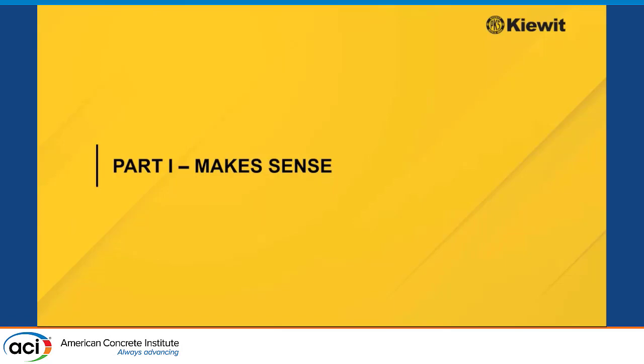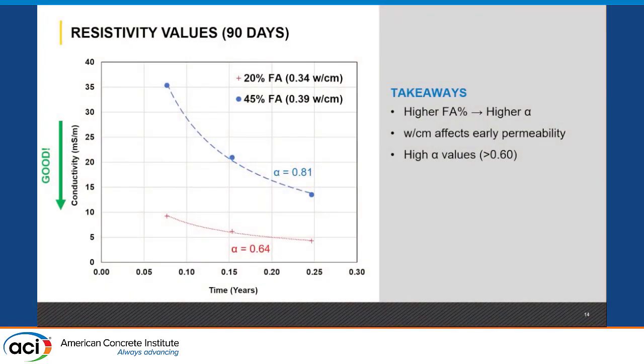So part 1 of the first cases that I have is when things make sense. And when things make sense, they're still challenging, but at least they make sense. This is from the first project where we use fly ash. And we see some very, very key takeaways that are logical. The more fly ash you use, the higher your alpha value, 0.8 with 45, 0.64 with 20%. Awesome. We see that water cement ratio is affecting your early permeability. That's logical. High water cement ratio, high permeability, and so on.